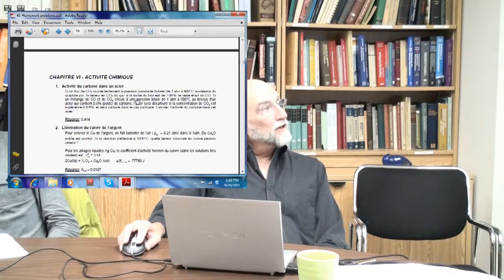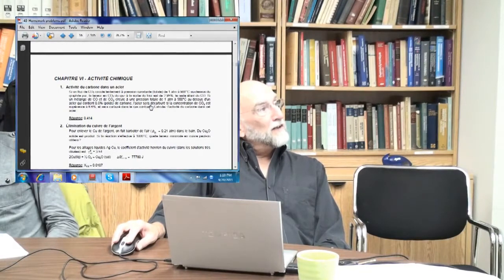If a mixture of CO and CO2 circulates slowly at 1 atmosphere total pressure above pure graphite, then the CO2 in the gas at the exit is 2.95%, the rest being CO. Then we do the same thing, but instead of pure graphite, we replace it by steel, and the steel will be decarburized if the concentration is greater than 6.6%, and carburized otherwise, which is just saying that's the equilibrium percentage.